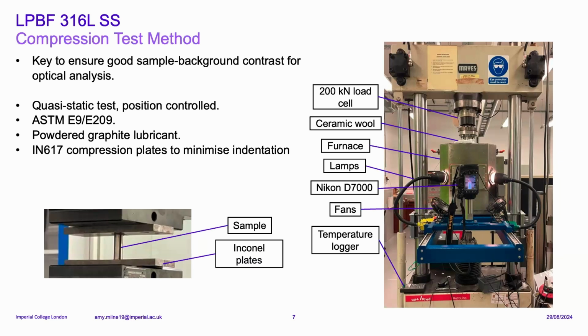There was ceramic wool used at the top and the bottom to prevent any heat escaping and keep a constant temperature gradient. And the lamps were used to illuminate the sample so that I could use the camera to take pictures at 5-second intervals and monitor the axial and radial deformation throughout the test. The fans are pointing in front of the camera lens to remove the effect of heat haze, and I also had a thermocouple attached to the top and bottom plate to make sure that the temperature gradient was stable. A powdered graphite lubricant was also used on the top and bottom of the sample to prevent any barreling and make sure I got reliable results. The ASTM E9 standard was followed for the room temperature test, and then E209 for high temperature.